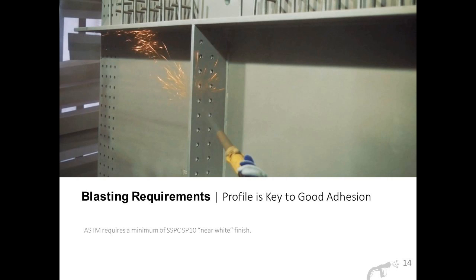So what's a coating without talking about blasting requirements? I think that we'd all agree that getting a good surface profile and good surface preparation is probably the key to getting good adhesion for almost any corrosion protection option. ASTM requires a minimum of SSPC SP10 near white finish. Blasting can be done either semi-automated or by hand, depending on the available equipment. In this case, what you're seeing in the picture here is somebody blasting the steel girder by hand to provide the necessary profile for a metallized surface.